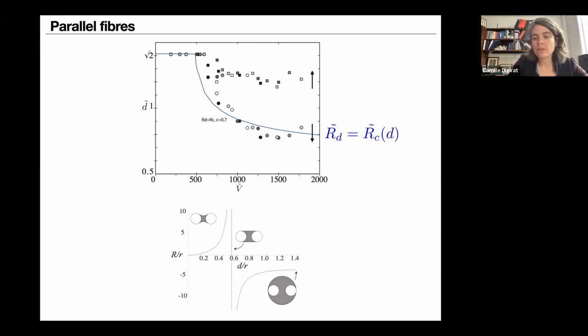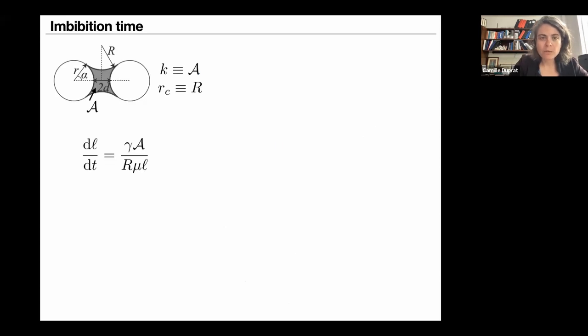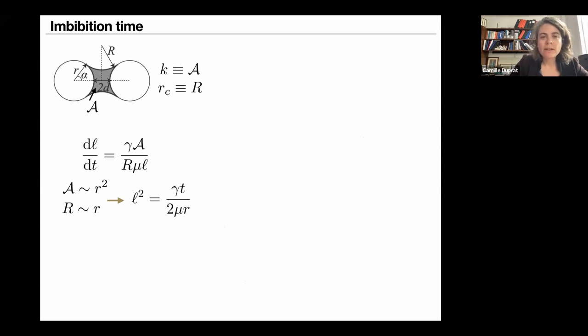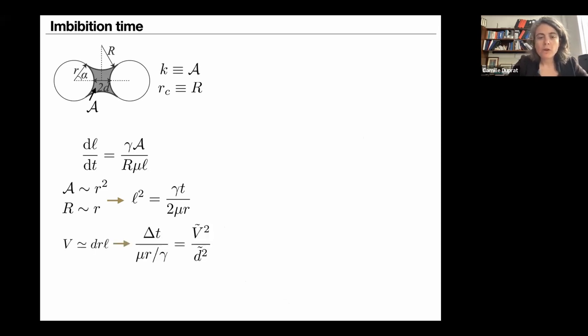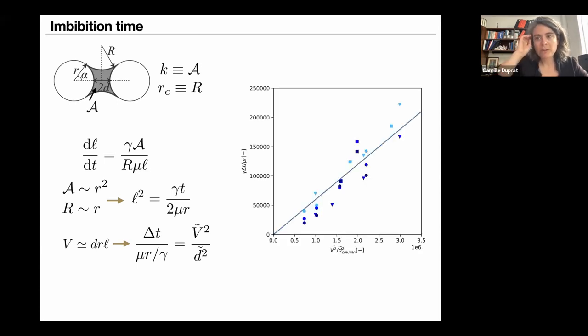The upper limit of column formation remains slightly below √2, because the columns are metastable near that limit — the radius of curvature changes very little between d/r ≈ 1 and 1.4, so the transition to drops can occur at any point in that small region. The typical wicking time scales as volume squared divided by the square of the fiber separation, consistent with experiments: decreasing the fiber distance dramatically reduces absorption time.